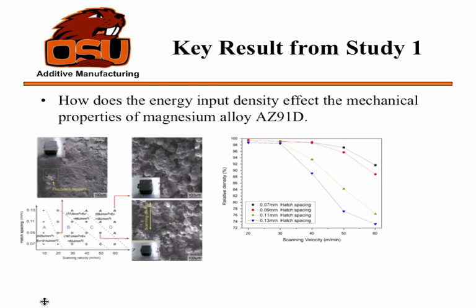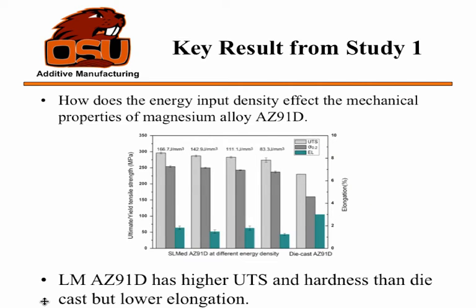And then they also looked at hatch spacing and its effect with scanning speed on the relative density. So generally you want to keep those fairly high so that you can achieve good mechanical component properties, although there are some applications where controlled porosity is good, especially for biodissolvable, biocompatible things.